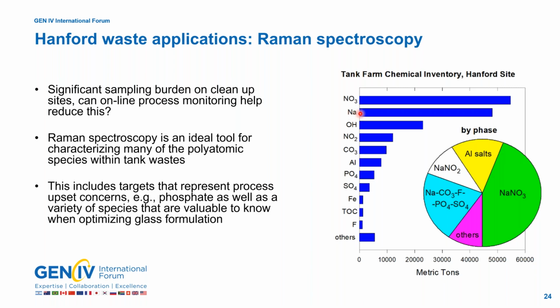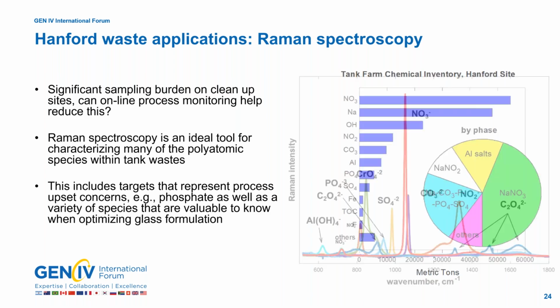If you sum up the major constituents, which are sodium salts of nitrate, hydroxide, nitrite, carbonate, aluminate, phosphate, and sulfate, those 6 or 7 constituents add up to 95+% of all the solid components in all of the tank waste out in the Hanford area. If you exclude water, 95% of what is in the tanks are Raman active sodium salts. And that's why we use Raman spectroscopy, because you can measure 95% of the constituents in one spectrum.